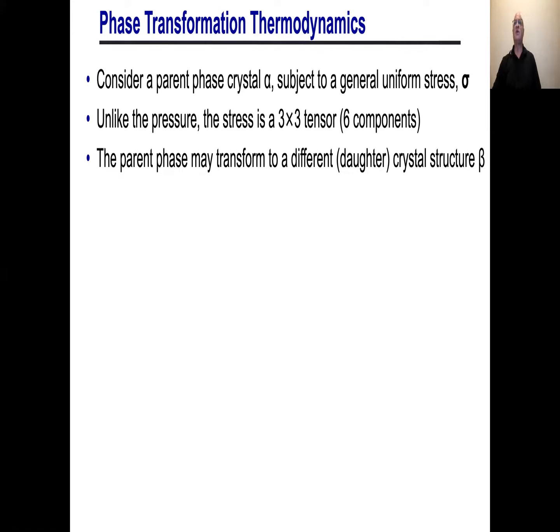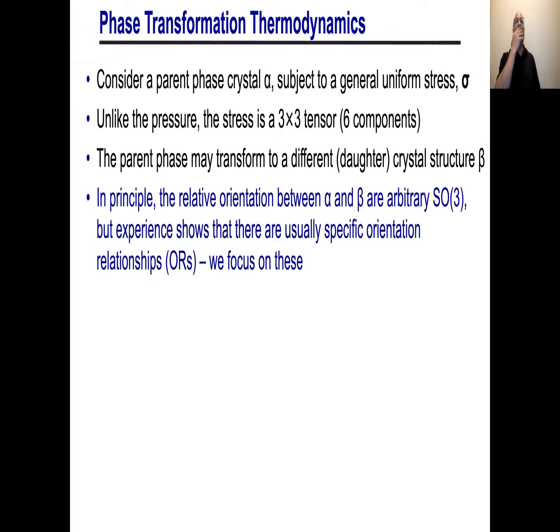And then we want to say, well, this thing will transform into a daughter crystal structure. It'll transform from the parent to the daughter, and we'll call the daughter phase beta. So we've got an alpha possibly transforming to beta. And in principle, the relative orientation of alpha and beta is arbitrary. It could be any orientation. That's an SO(3), a 3-parameter rotation. By the way, we started by doing this in DFT, exploring over all of SO(3). But we found out very quickly that the classic orientation relations for these phase transitions really do work. So I'm not going to bore you with showing you how to do the calculations for all possible grain orientations, but we're just going to stick with a few of the well-known orientation relations.